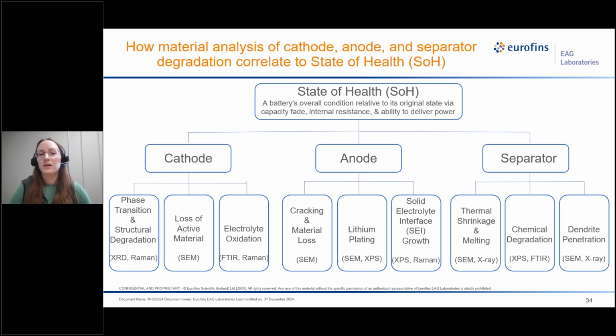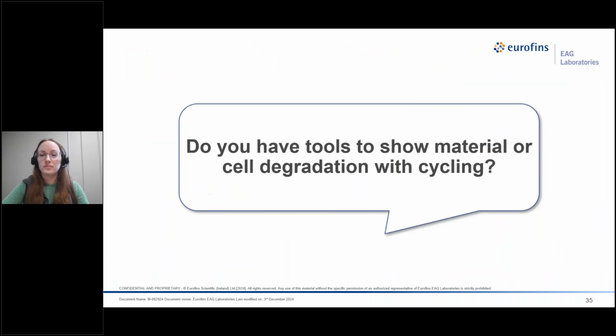And with our separator, we would also see thermal shrinkage and melting that we can also look into with our SEM or X-ray, chemical degradation with our XPS and FTIR, or dendrite penetration with SEM and X-ray. So now we can begin to see what tools we have to show such material and cell degradation, but with cycling.